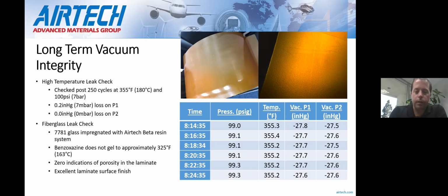We also did a fiberglass leak check. It's more a way to isolate that, even with that 0.2 inches of mercury, the tool itself in the field area is not losing vacuum integrity.